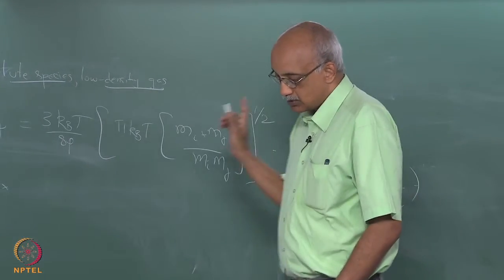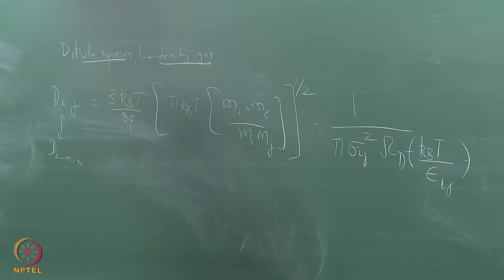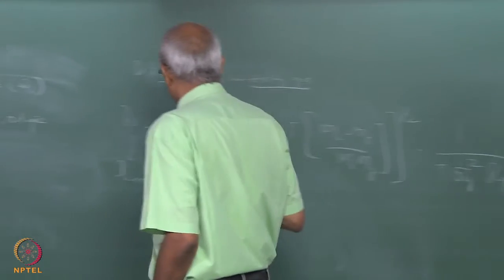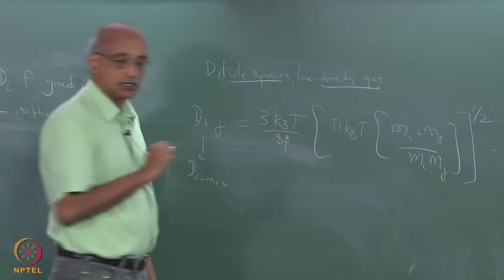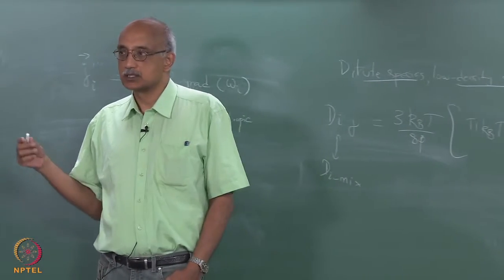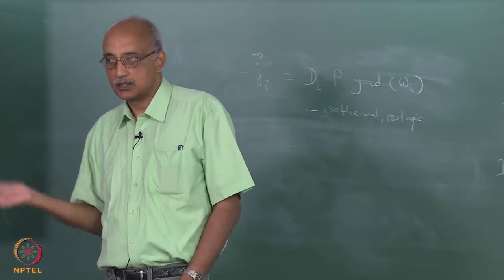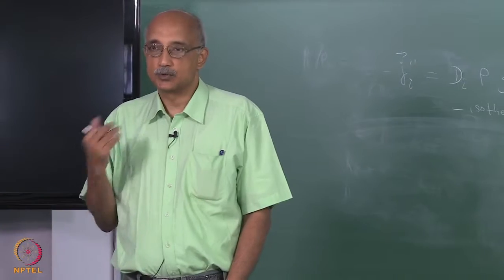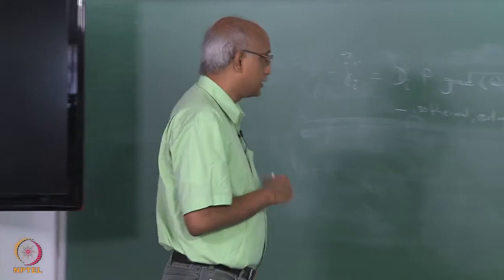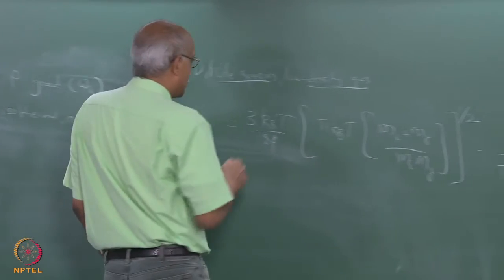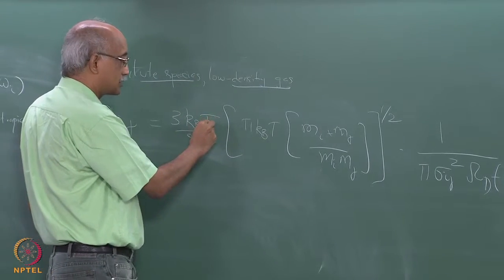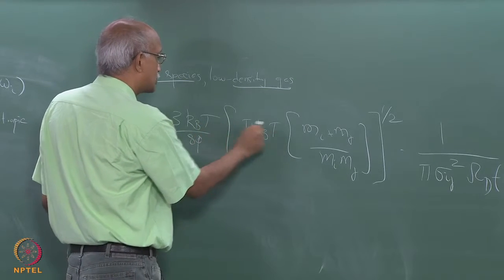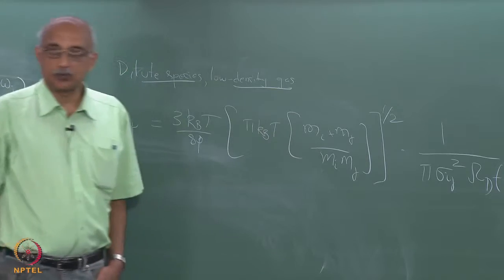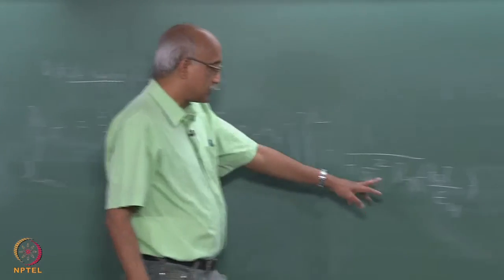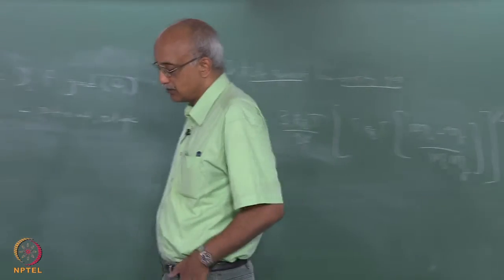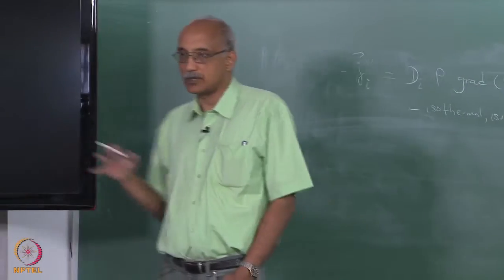Okay, so if you compare this expression to what we wrote down for viscosity and thermal conductivity, the key differences are pressure is now a key term and it is in the denominator. As pressure increases, diffusivity decreases, which is why if you want to enhance diffusion rates, you use low pressure systems. So, that is an important thing to keep in mind. The second thing to keep in mind is here the temperature dependence is basically close to T times T to the power half, or roughly 1.5, but again there is some temperature dependence here. So, the actual temperature dependence of the diffusion coefficient is roughly T to the power 1.5 to 1.8.